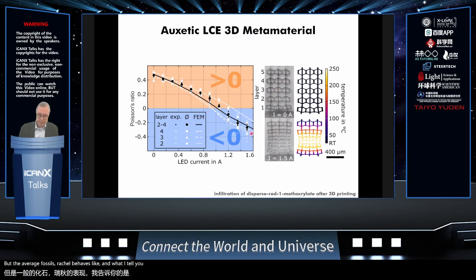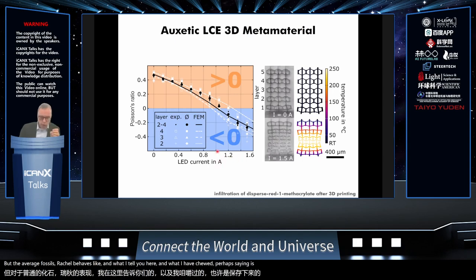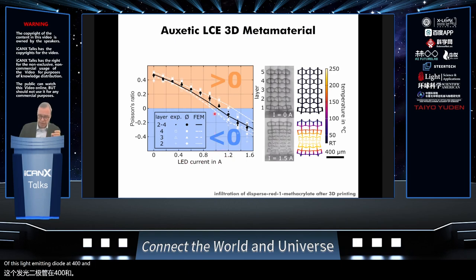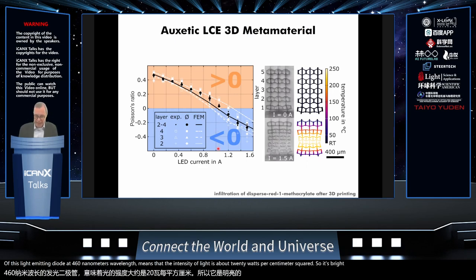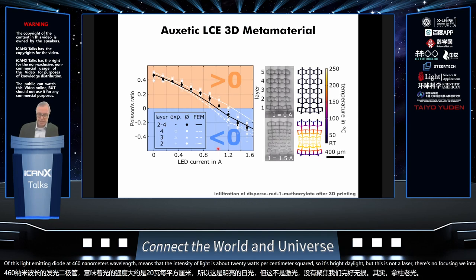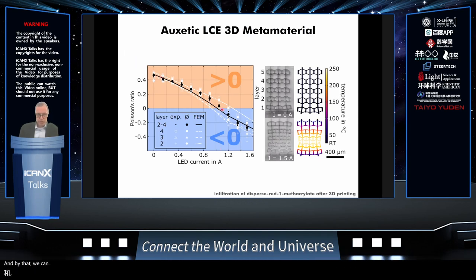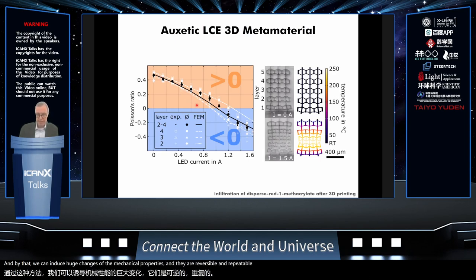It's not perfectly homogeneous over the structure, but the average Poisson's ratio behaves like what I tell you here. And what I should perhaps say is 1 amp of this light emitting diode at 460 nanometers wavelength means that the intensity of light is about 20 watts per centimeter squared. So it's bright light, but this is not a laser and there's no focusing. We in fact take the collimated light emitting diode, and by that we can induce huge changes of the mechanical properties, and they are reversible and repeatable many, many times.